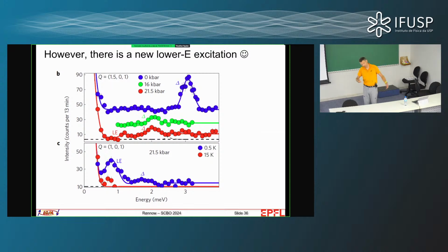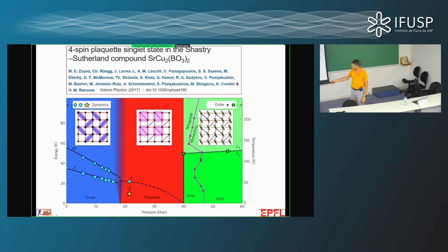Okay? And so, being a little bit brave, we said, well, there's a new excitation. If there's a new excitation, maybe that's because we have a new ground state. And so maybe what we have is that we went from this singlet product state over here into a new ground state, a plaquette product state over here, and it's just coincidental that in this new phase that has a set of excitations, one of the excitations in the new state has the same energy, and by the way, also the same intensity as the triplet excitation in the previous phase. And then this new one here should be proof that we're in a new state.